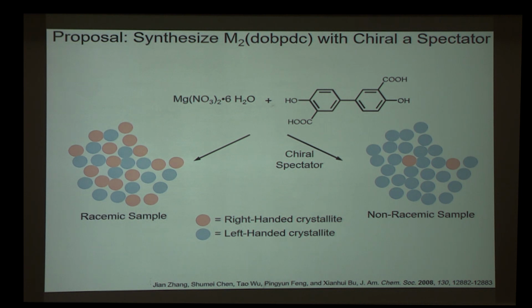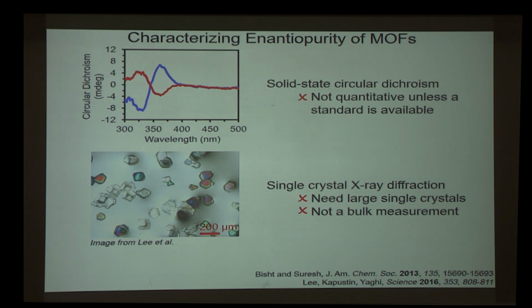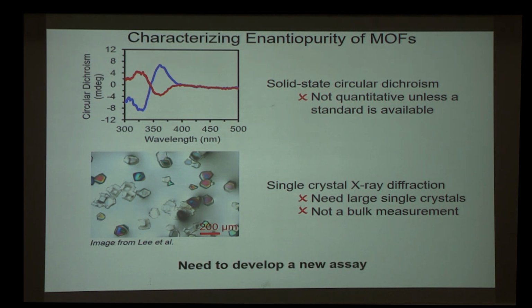Before attempting this, I had to think about how I could even characterize the material to determine if I had made something that was non-racemic. There are a few methods in the literature for this. One is solid-state circular dichroism. However, this method is not quantitative unless you have an enantiopure standard of your exact material of interest, and we did not have that. Another approach is single crystal X-ray diffraction. However, we did not have sufficiently large single crystals for this to work. So the established techniques were not going to be suitable, and I needed to develop a new assay to characterize the enantiopurity of my material.